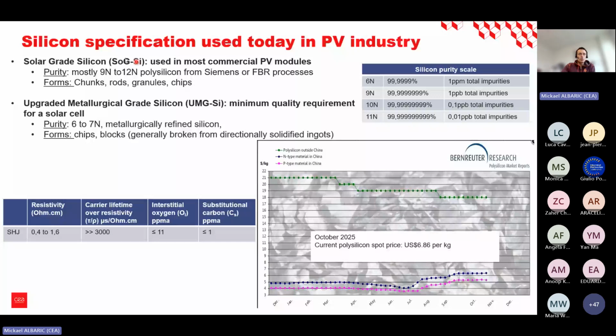I also give you information regarding another methodology: the upgraded metallurgical grade silicon, which reaches a purity level a little bit lower compared to the Siemens process. But we consider a minimum quality requirement for solar cell manufacturing if we can reach a purity level close to 7N. But you have to have in mind that the main part, close to 100%, is coming from the Siemens process.